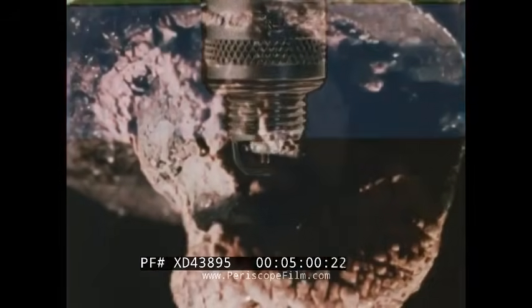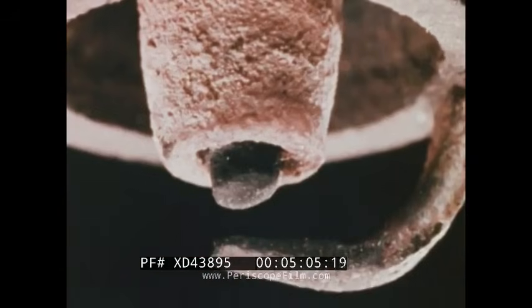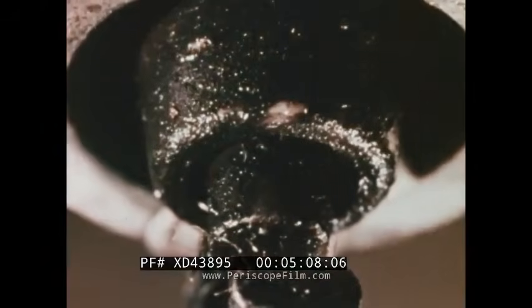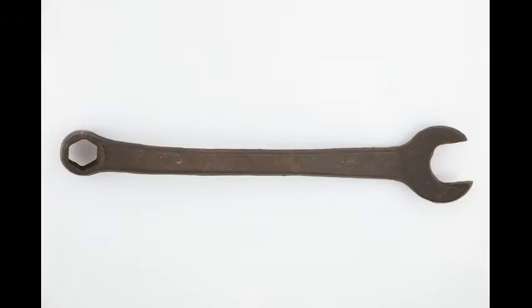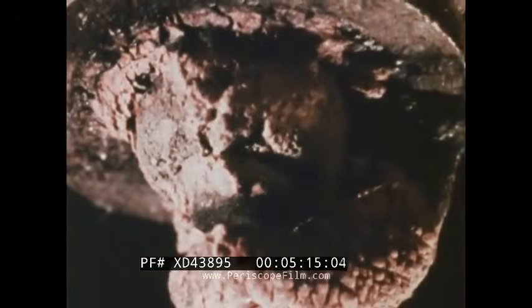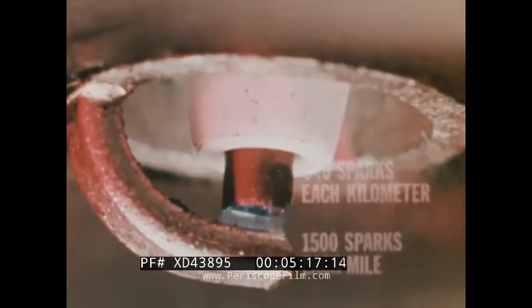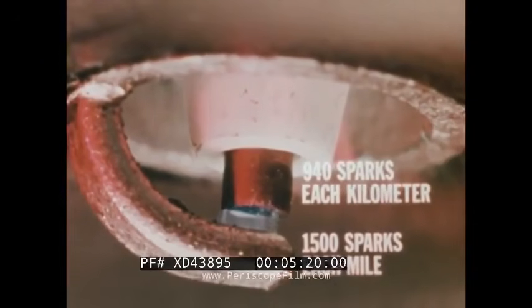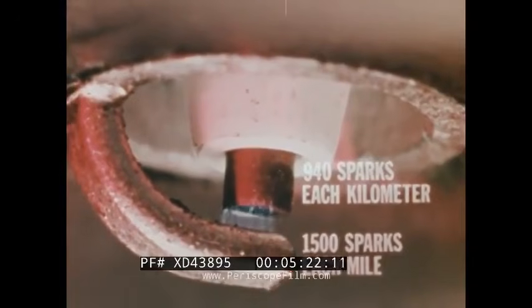Every time the engine fires, the lower end of the insulator is exposed to hot combustion gases. A moment later, it is cooled by incoming mixture and by heat flowing into the cylinder head. It is shaken by engine vibration, struck by pressure waves, contaminated by oil, carbon, and metallic fuel residues, and clamped inside a steel shell that expands differently when heated. A microscopic pore can become an electrical pathway. A tiny crack can grow under thermal cycling. A weak, glassy region can soften or conduct current at the worst possible moment.